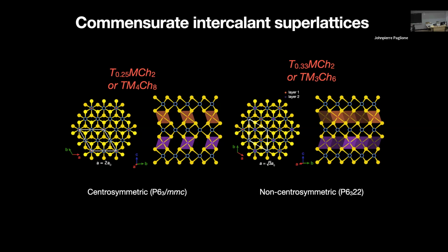And so for a 1:4 ratio of the intercalant to the host lattice, so this is the 0.25 or 1/4 intercalation, or a 1:3, so the 0.33, you can construct respectively a centrosymmetric superlattice that has a 2x2 superlattice structure. So the new unit cell is twice the size of the original TMD unit cell, or a square root of 3 by square root of 3 superlattice structure.